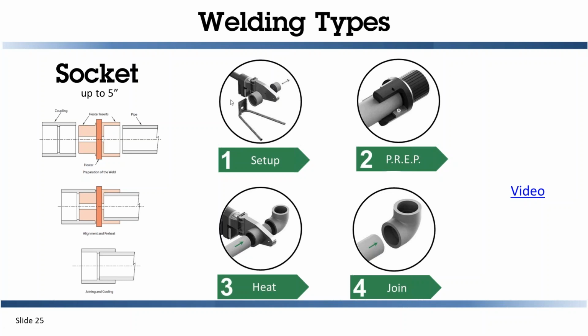So then we have a highlight here. We have a setup of the tool. We have preparation of that with the polyolefins. Any material that can oxidize, we want to remove that oxidation that's just naturally occurring on the pipe. That's the polypropylene and polyethylene materials. And that makes sure that we have a good chemical resistant bond between the coupling and the pipe.